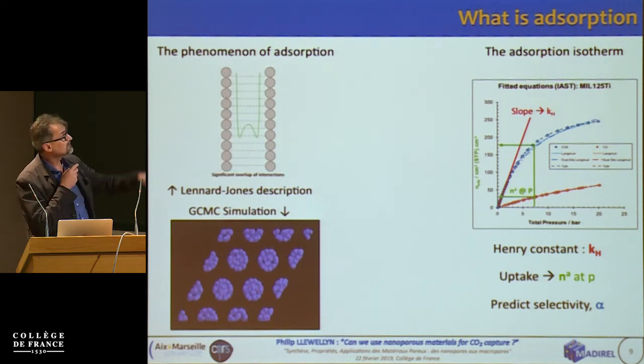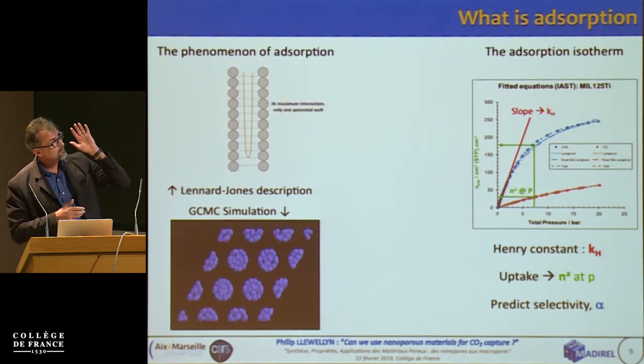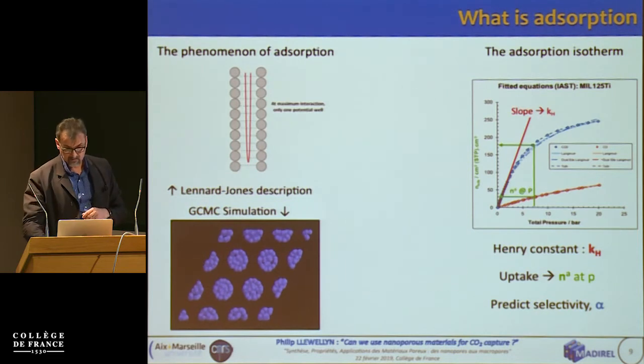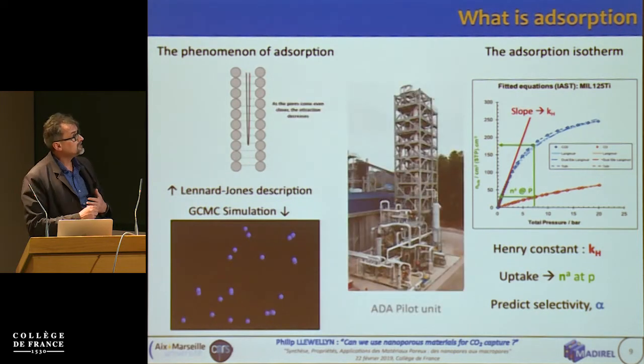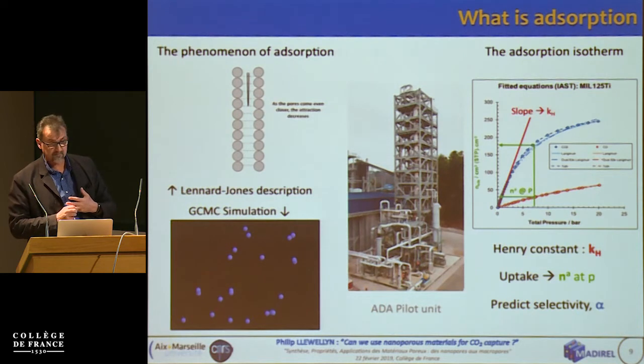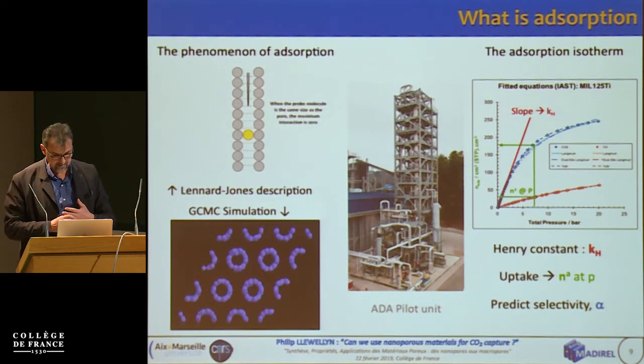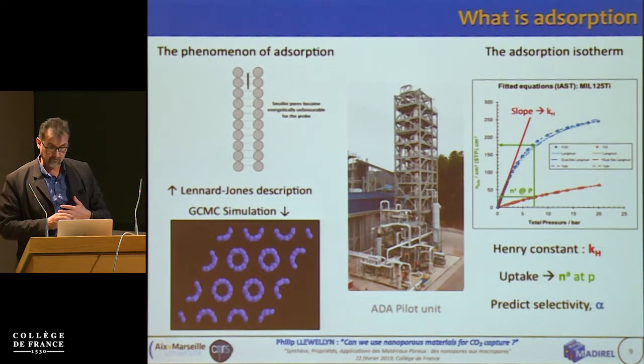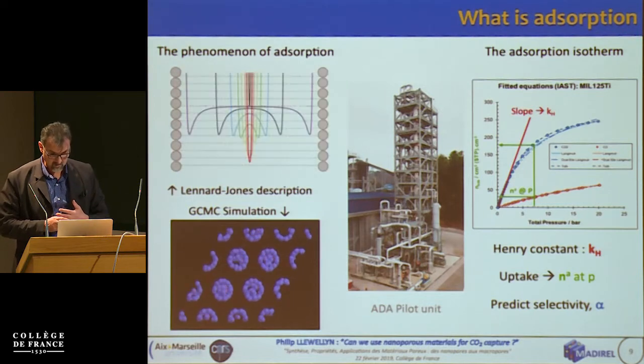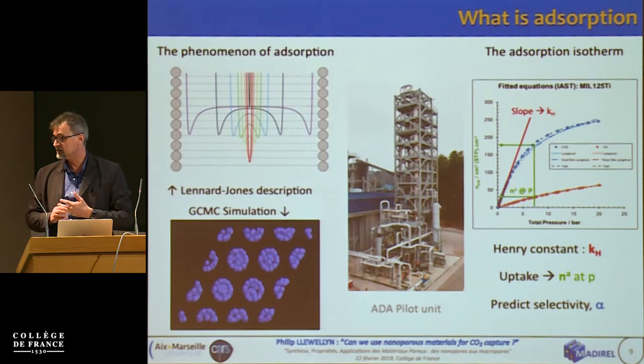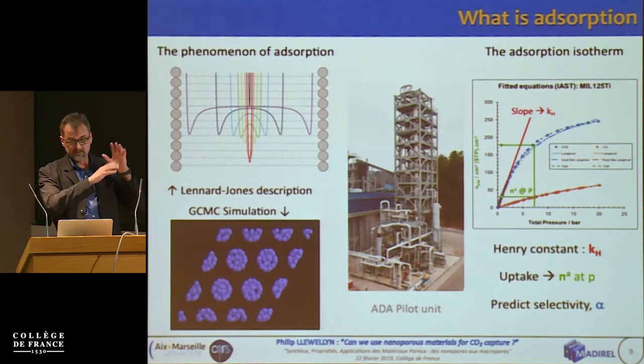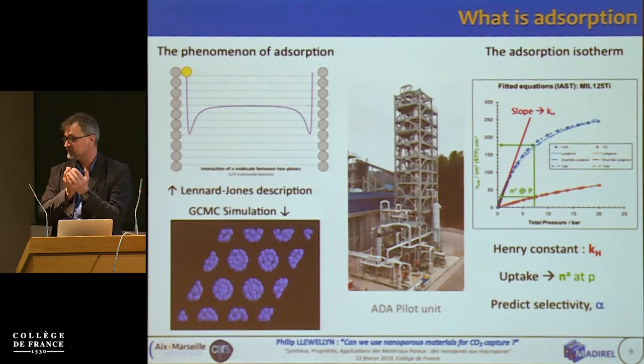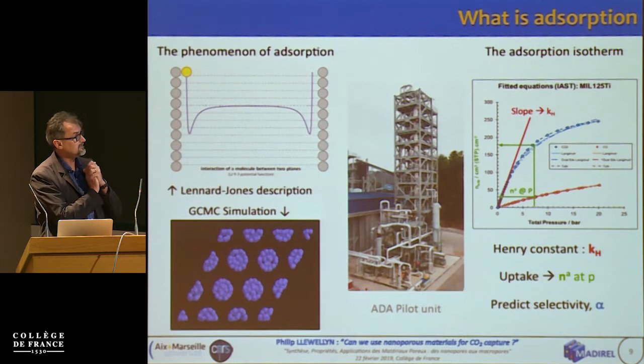So fine. We have the models on the left-hand side. We have what we can do in the lab on the right-hand side. And we can then go to the pilot plant scale. So this is a pilot plant which I think is in the USA, an ADA pilot plant, used for CO2 recovery, with an amine functionalized silica. So CO2 recovery using amine functionalized materials has already been tested.